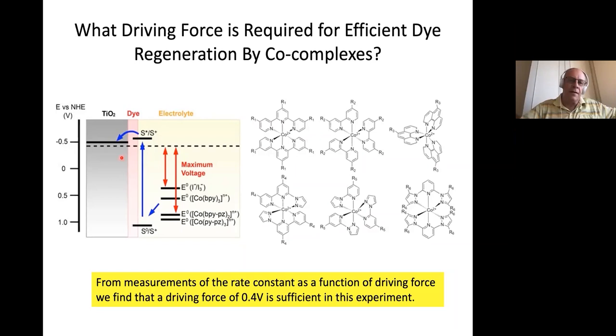On the other hand, we also lose driving force. It gets smaller and smaller potential drop here. And at some point, we have the optimum where we can't go much lower here. And for cobalt complexes, that turned out to be 0.4 volt about. And that was a measurement we did, which is called the Marcus theory plot.